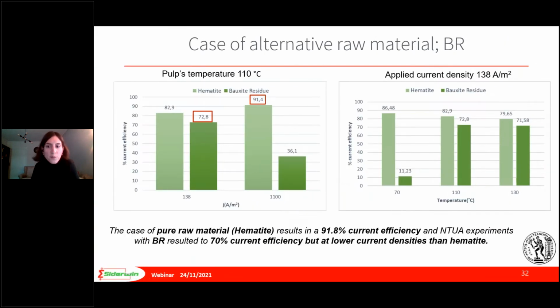Comparing the two raw materials, the pure hematite and the bauxite residue, we concluded that these two materials are very different. Bauxite residue achieved 70% current efficiency at 110 Celsius degrees, but for higher current densities, the bauxite residue Faraday yield reduced to 36%, when hematite yield is 90% and more. While researching the temperature effect, applying the bauxite residue's more efficient current density, hematite seems to result in higher efficiencies at lower temperatures than bauxite residue, for which at lower temperatures the efficiency decreases intensively. So the pure iron ore still results in higher Faraday yields at higher current densities, and bauxite residue electrolysis needs optimization to reach an increased current efficiency by applying higher currents to the system.